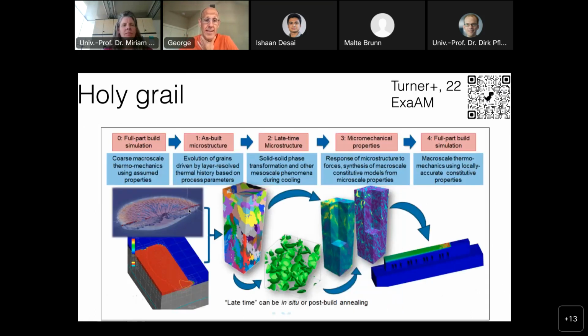The holy grail, as I said, is to be able to go from the melt pool physics, in which here we have the solidification, and here we have heat transfer, and actually Navier-Stokes equations, we have free surfaces. In fact, we have radiative heat transfer, and very complicated physics, plus the solidification for the metal, which will give us the final microstructure. Then, even after the process ends, because of the heating and residual heat, there will be some grain formation that will create a residual stress, and then we want to find some effective material properties using crystal plasticity, and then put these inhomogeneous material properties into a part simulation, in which then we're going to simulate the performance of the part